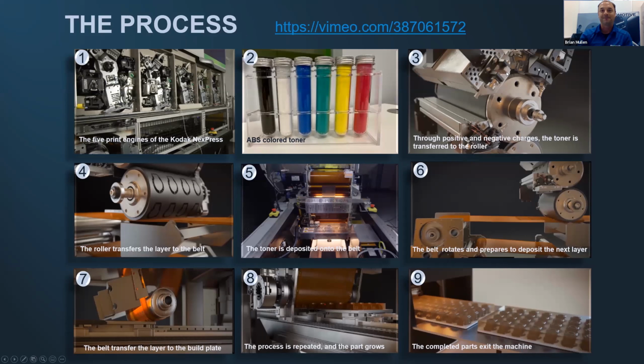But basically, through electrochemistry, we charge our polymer particles with a negative charge. It adheres to these positively charged cylinders. And the positive charges are only in certain sections that are being read by our software that creates these images and feeds them to our hardware. And then we can get really nice images of part and support. And in image five, you see a full layer that has been transferred to a belt. This is a continuous belt that moves through our step technology system until it hits step number seven, which is our transfuse roller. So in this area, there are part heaters that really heat up the incoming layer as well as the build, which is coming through this X stage right here.